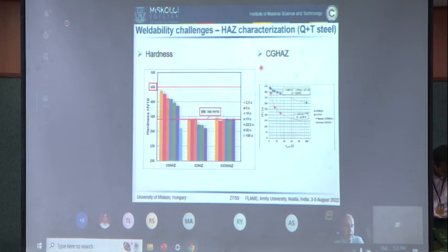If we consider the hardness properties and analyze the hardness in terms of cold cracking sensitivity, compared to the base material, we can say that as we reduce the heat input, the hardness increases, but generally there is no risk of reaching the requirement of 450, which would mean high cold cracking sensitivity. Softening generally does not occur much in these steels. Sometimes at high heat input in the intercritical zone, some softening can occur. Compared to the 960 with a conventional S355, we can see that at medium or high heat input there is a large difference in the hardness of the coarse grain zone. But as we go down with the heat input and the cooling time, the hardness values are quite close to each other.